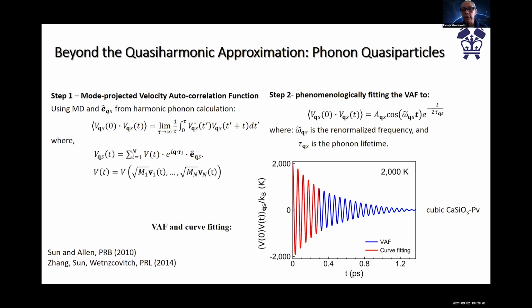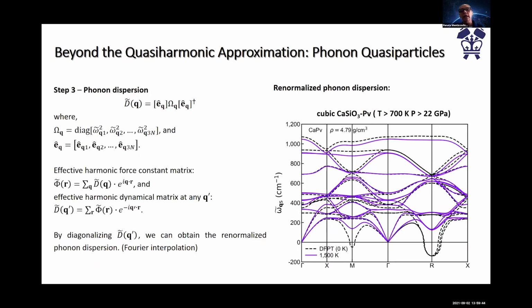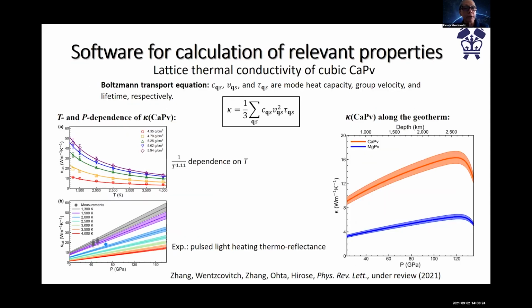In an MD simulation, we sample only a limited number of wave numbers, and we compute these quasi-particle properties only for the phonons sampled in the MD, but then we needed to extend and obtain the entire phonon dispersion. And we used the same technique that we used to draw phonon dispersions in harmonic phonons. For example, at 0 Kelvin, calcium silicate is unstable. There are instabilities, imaginary phonon frequencies at some points of the Brillouin zone, but with increasing temperature, these phonons are stabilized. This is very important for us. So at high temperatures the phonon quasi-particles are stable, and we can use the quasi-particle properties also to obtain thermal conductivity.